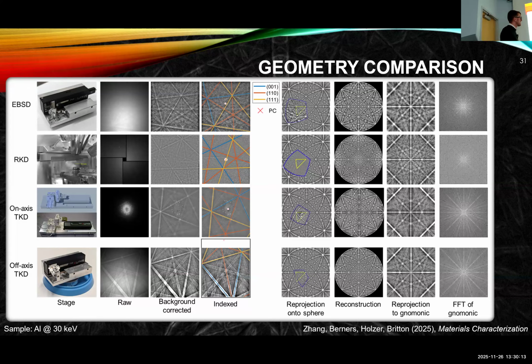And what we can do is we can take each of these experimental diffraction patterns and put them back on the reference sphere. Here we present it in a so-called stereographic projection to make it flat. But effectively, blue is what we saw in practice. And then we can play a cheap game of origami.